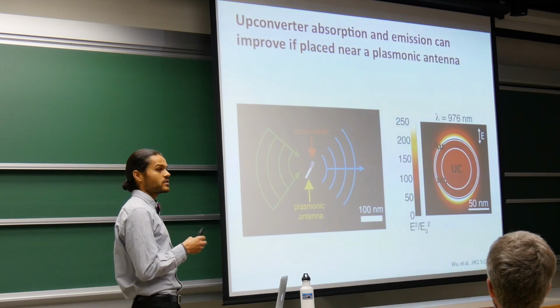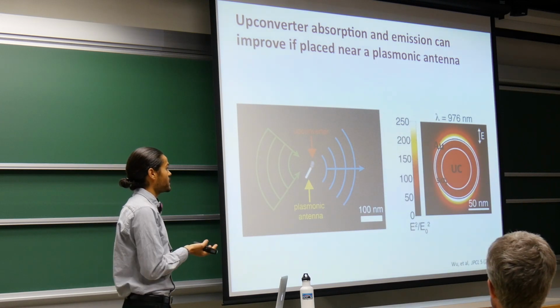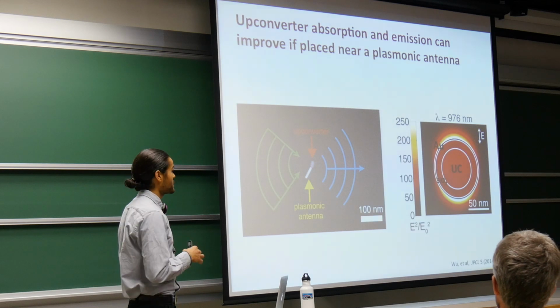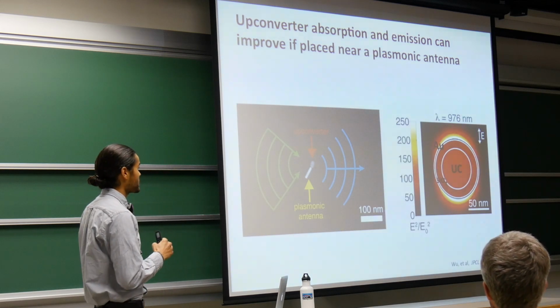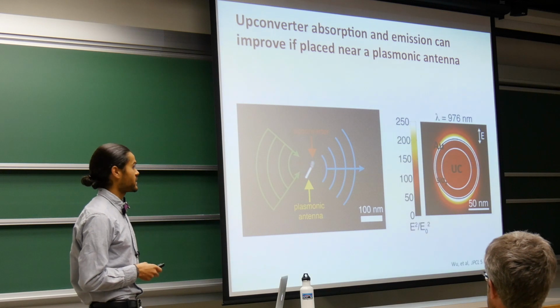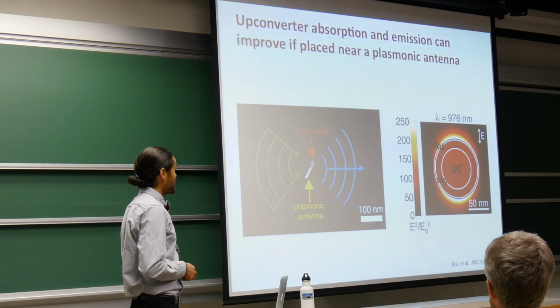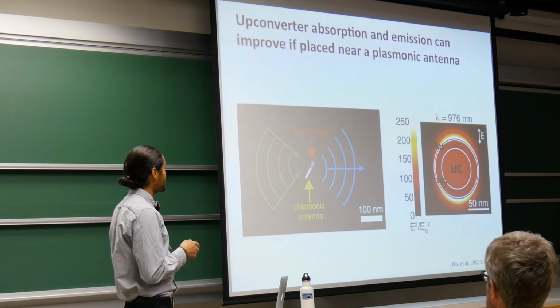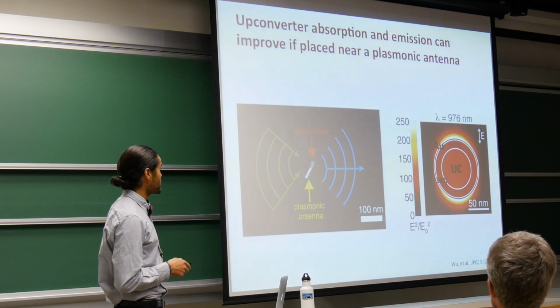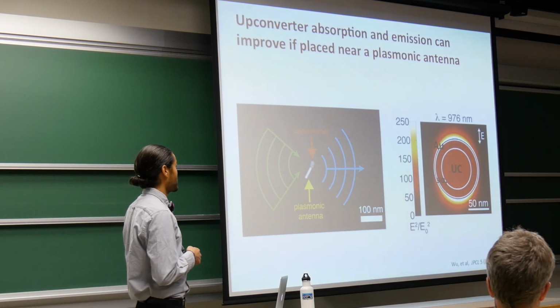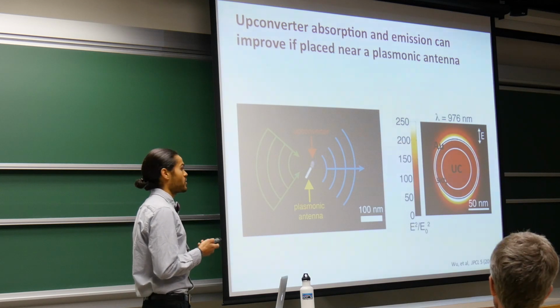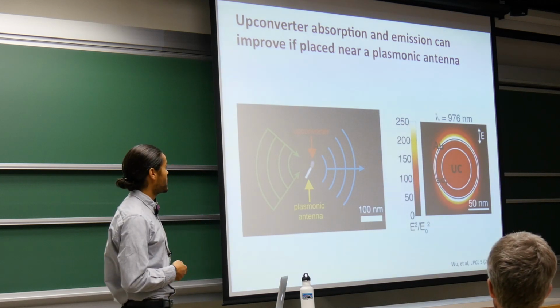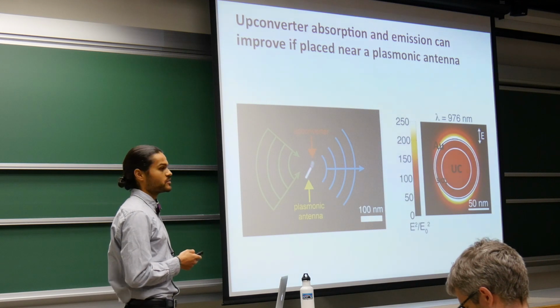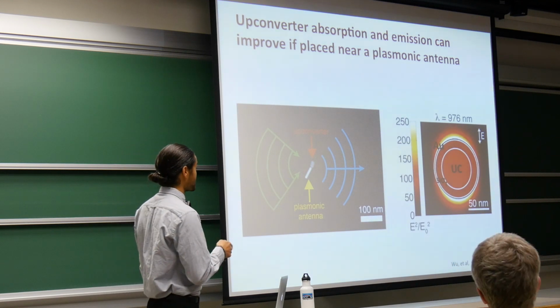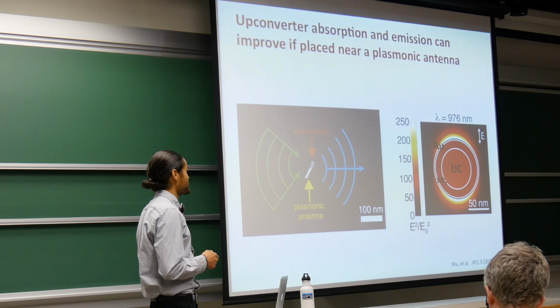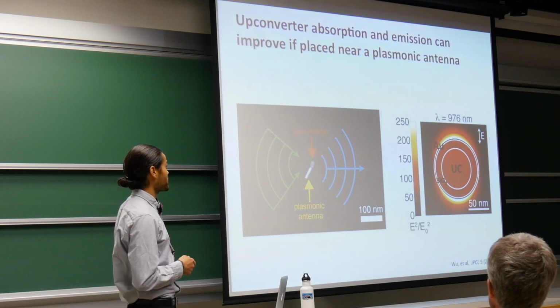So here we have a spherical upconverting particle that's coated in a small dielectric spacer layer to prevent recombination or quenching, and then finally a small metallic shell, in this case gold, for the simulation. Depending on the geometry and the materials used for this particular structure, we can tune the plasmonic resonance of this structure to overlap, for example, in the near-infrared, where this upconverter absorbs most strongly. As you can see, we can achieve intensity enhancements of around 50 to 100 throughout the upconverting particle.